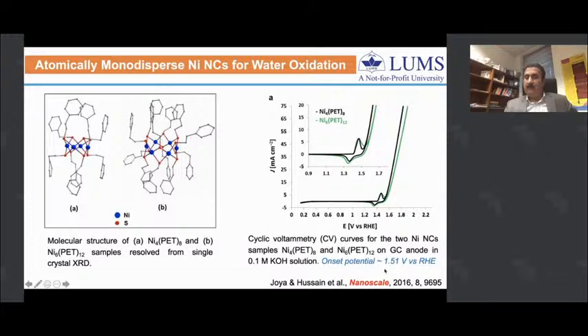For example, they were able to oxidize water at 1.51 volts versus the reversible hydrogen electrode potential. But the problem with these nanoclusters is that because they were really soluble, like metal molecules, you cannot reuse them.